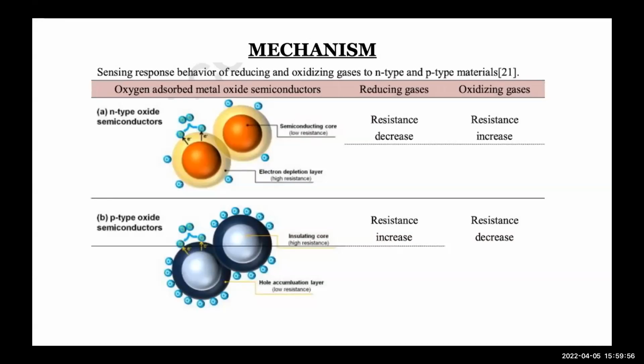So here you can see the diagram of the mechanism. Basically the gas sensing mechanism of metal oxide semiconductor is mainly associated with surface phenomena, which contain gas. Oxygen ions adsorb on the surface of the metal oxide semiconductor. The semiconductor nature of metal oxide is important for gas sensing because, as you can see here, the semiconductor core and insulating core. So when air molecules come in contact with the crystallographic surface of the metal oxide semiconductor, oxygen ions trap the excited electrons from the conduction band and form a depletion layer on the surface of the metal oxide semiconductor, as you can see in the diagram.